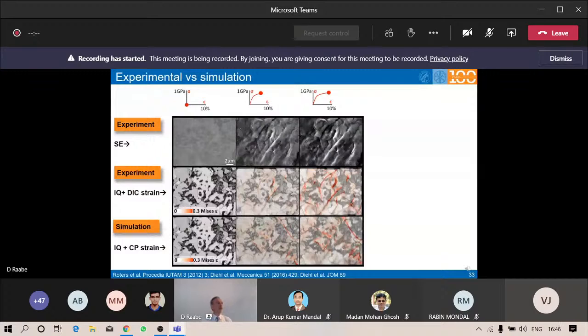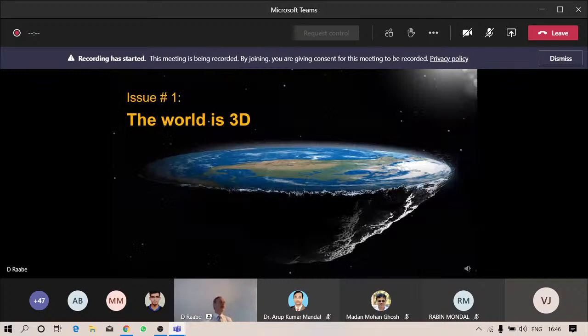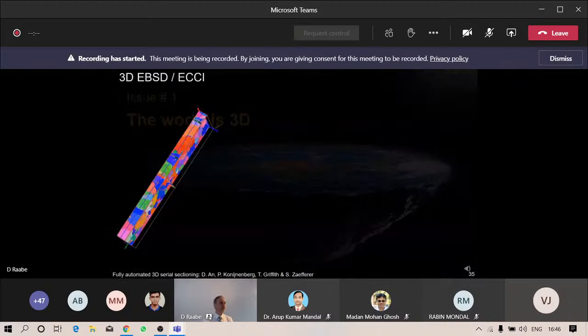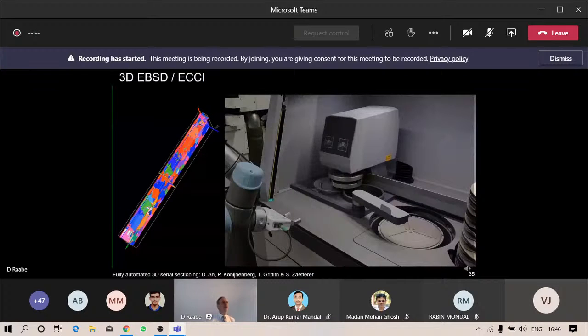the agreement between experiment and simulation, like you see in the second and third row here, then you can see nicely that while some of the features, particularly around the hard martensite particles, agree quite well between simulation and experiment, other features deviate quite a bit. And the reason for that, as sketched with this little picture, is that of course the microstructures are in reality three-dimensional. And this in part affects the surface results of the strain and stress that you measure.